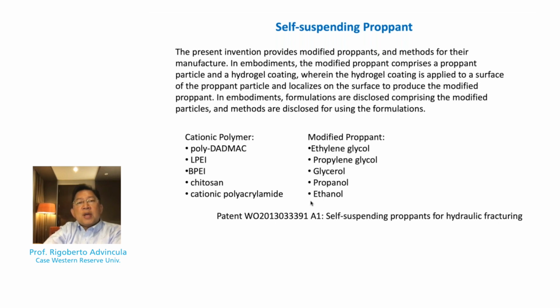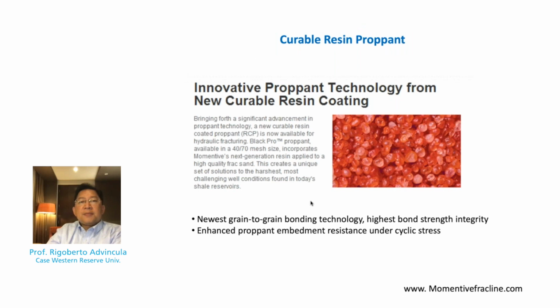So this composition together with the hydrogel essentially swells the shell or the polymer shell around the particle. So this would have involved some coating process where the hydrogel is fixated on the particle, and therefore when resuspended in water, they're able to float, viscosify, or in other words, the swelling of the gel basically lowers the overall specific gravity of the particle itself.